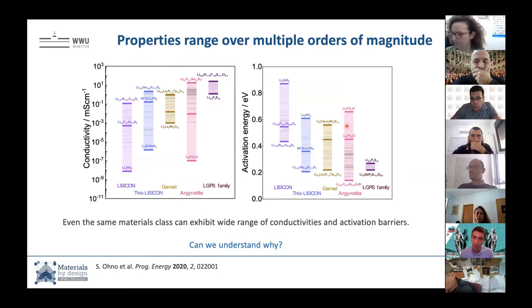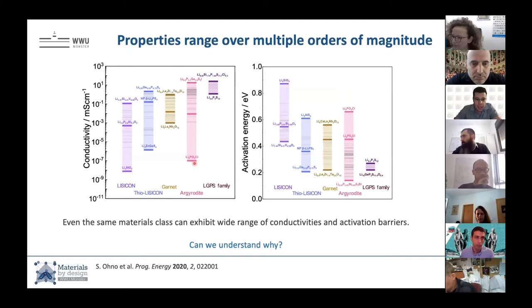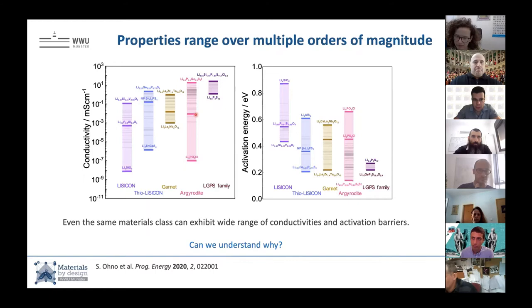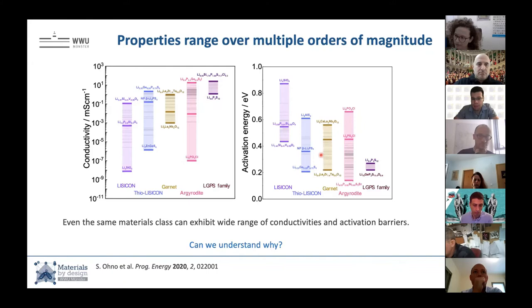This is where my group tries to tackle things. We've compiled conductivities in certain material classes, and all these bars represent one materials class or one structural family. If you look at the argyrodites, for instance, the conductivities based on composition can change orders of magnitude, and even the activation barriers change quite significantly. So within the same structural family we can have tremendous changes in ionic transport, and the question is can we understand why and use that knowledge to guide materials design.